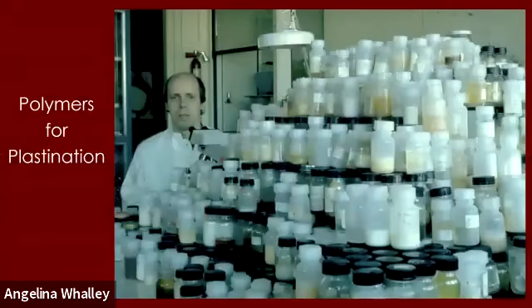But Gunther was very clever. He absolutely knew that this was dependent on the polymer. He didn't use the right polymer. It did shrink because the polymer had only a very short pot life, so impregnation wasn't long enough. And it turned black because the polymer he used didn't have the right optical properties. So he knew it was just a matter of developing the right polymers. And this is what he actually focused on.